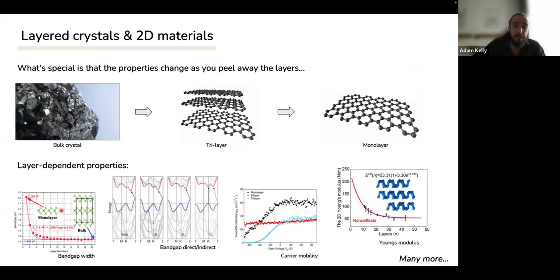So for example, with something like MoS2, a semiconductor, as you bring down the number of layers, the band gap changes. So we have tunability in here with layer number. Also, the band gap can change from direct to indirect as you go down, so this also gives us opportunities to work with light properties, optical properties. The mobility changes, of course, as you go down in layer number from tri-layer, bilayer to monolayer because you have screening and scattering effects. And then, of course, the elastic stiffness or the Young's modulus will change too because it's much easier to bend a single card than it is to bend something thick.